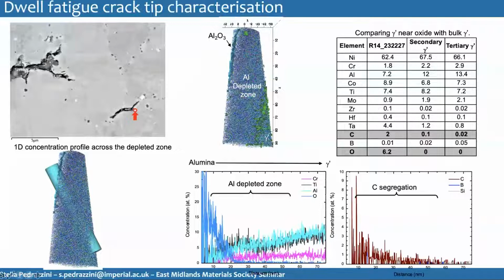And then I wanted to take a second sample that was from the secondary crack. According to EDX, the secondary crack sort of looked mostly like alumina, and it was mostly alumina. So I got a sample from here that is alumina on one side and then going all the way into gamma prime. So there's an aluminium depleted zone and then gamma prime on the other side. And in this case, it's quite interesting because in most of the literature, the sulfur is reported to go at the alumina metal interface, and it's not there.